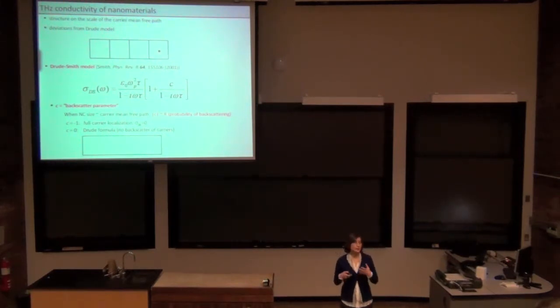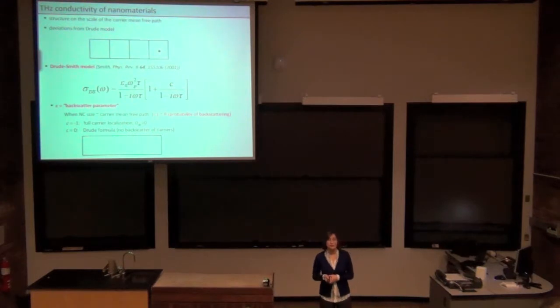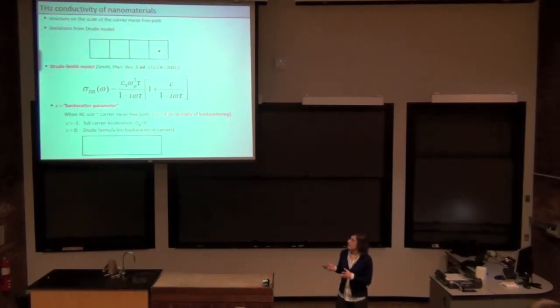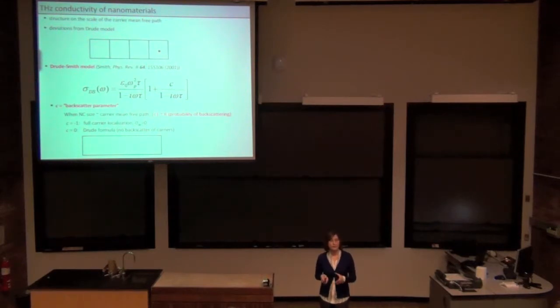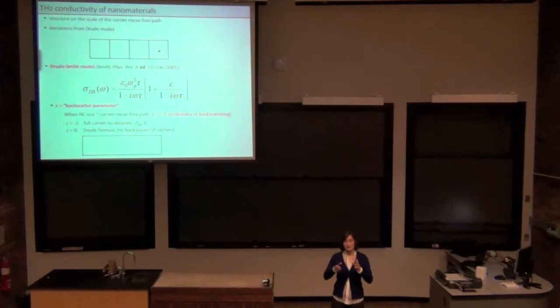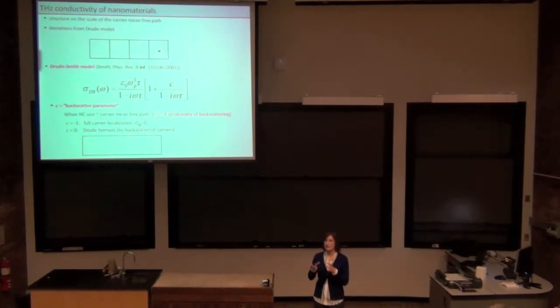There was some discussion of what this parameter really means physically, and we've done some extensive Monte Carlo simulations, which I'm not going to show, but the takeaway is that when the size of the nanocrystal is on the order of the mean free path, the absolute value of the C parameter is approximately given by the probability that when the carrier encounters the boundary, it's going to scatter back rather than go forward. So it defines how localized the carriers are in these nanograins.